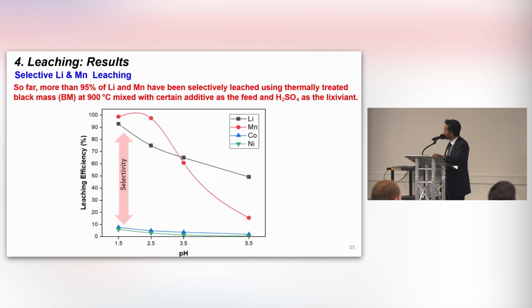And we also tried another type of selective leaching, specifically for lithium and manganese. In this study, we used the black mass obtained from the thermal treatment at 900 degrees, and here we use certain additives to change the crystal structure. As a result, we observe that more than 95% of lithium and manganese could be leached out at a pH around 1.5, while most of the nickel and cobalt remain in the leach residue.